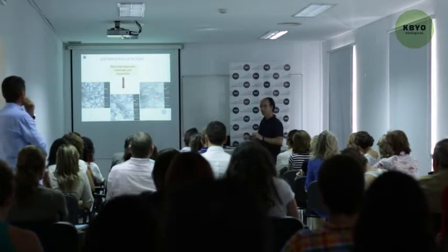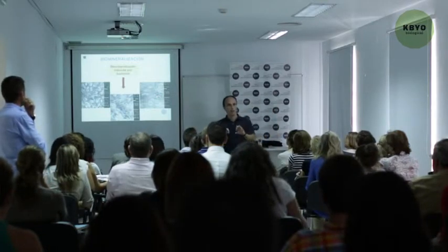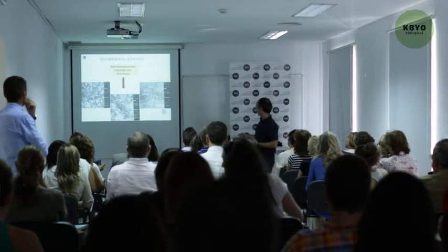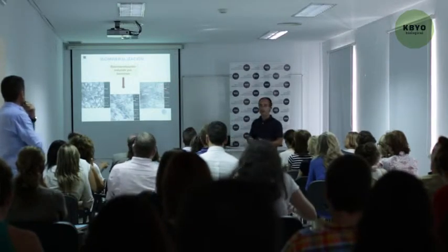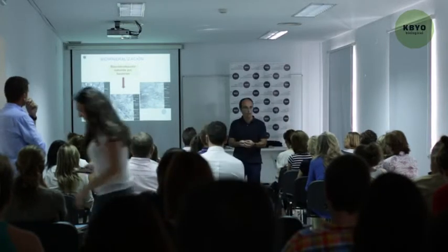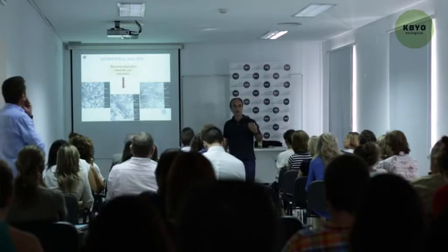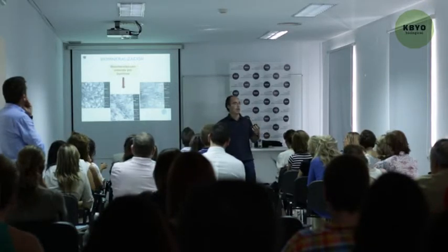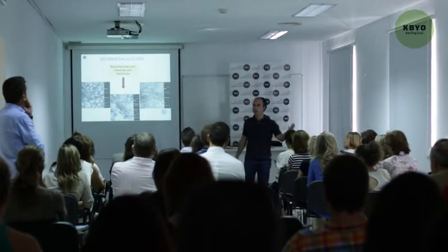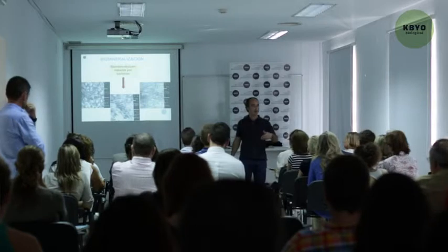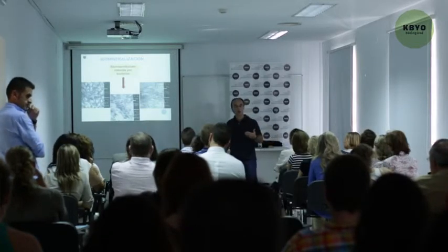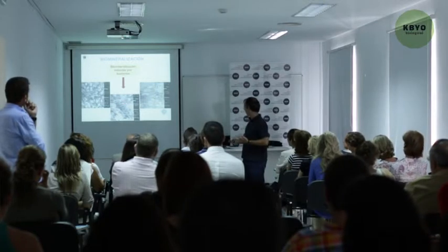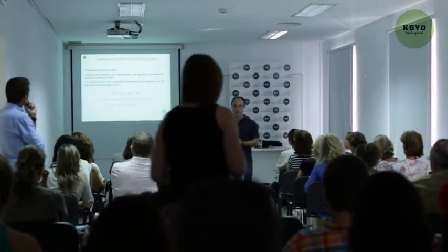The creation of carbonate by bacteria can appear because of the degradation of amino acids generating ammonia. Ammonia increases the pH of the medium and creates carbonate in the presence of CO2, generated by bacteria or absorbed from the air. This carbonate, in combination with calcium supplied by us, makes those bacteria generate calcium carbonate. So here we can see a new material that can consolidate a rock. This method of consolidation has been patented.